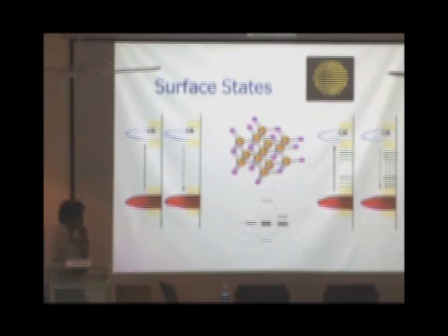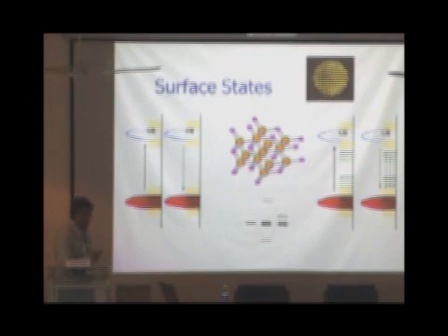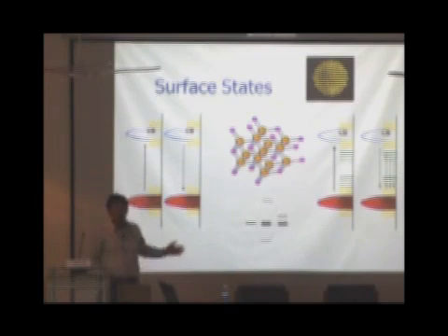Now, interestingly, if these dangling bonds have transition dipole moments so aligned, which of course we have no control over as of now, but if they are so aligned that there is a definite possibility, so the possibility of transition is non-zero, then we can get emission across these. And that emission would be less in energy compared to the band gap energy.